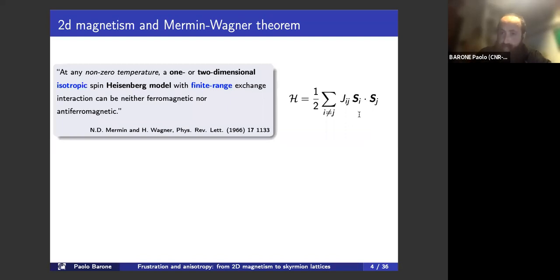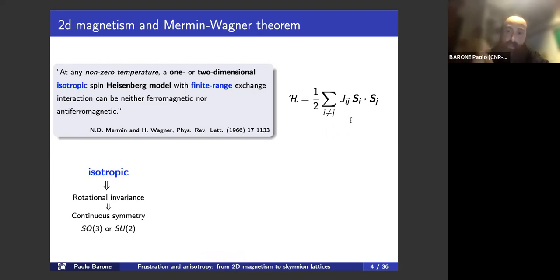The coupling is just a scalar, and typically it's assumed to be relatively short range. So the typical model assumes just the first, second, and third nearest neighbors. And the point is that this model is isotropic. What does it mean? That it's rotationally invariant, because the energy described by this Hamiltonian just depends on the relative orientation of the magnetic moments. And of course, that means that it underlies a continuous symmetry, which is SO(3) in the case of classical spins, or SU(2) in the quantum case.